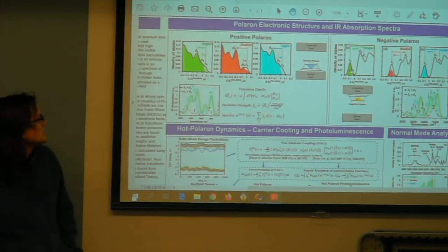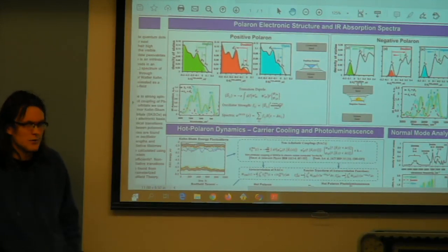I basically saw that qualitatively the electronic structure is the same. We still have a gap here, the sub-gap, which we wanted. I think it was a little wider with the hybrid functional. And there are the same characteristic trends with where the peaks were in the states. So in terms of electronic structure, there wasn't that big of a difference for what we're trying to focus on.